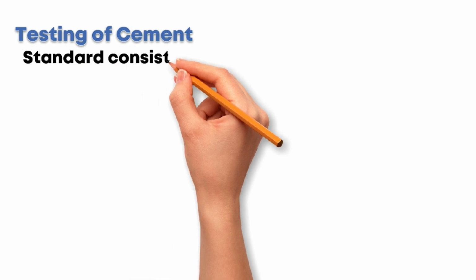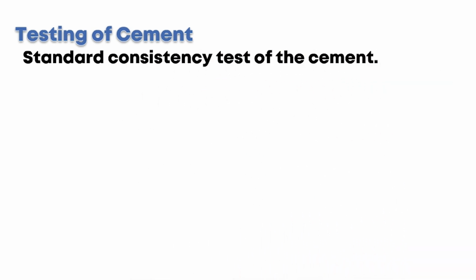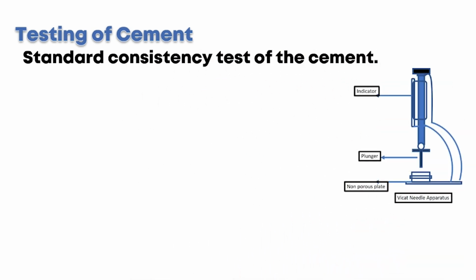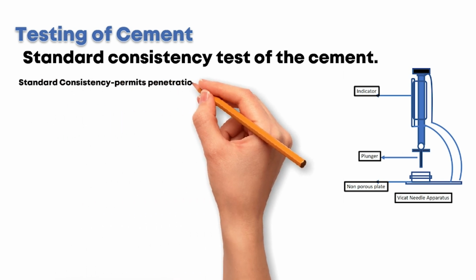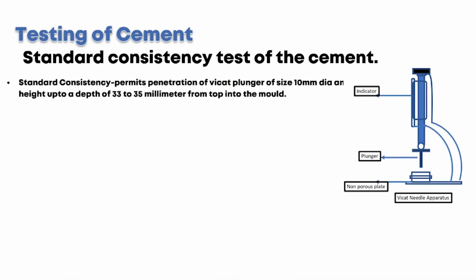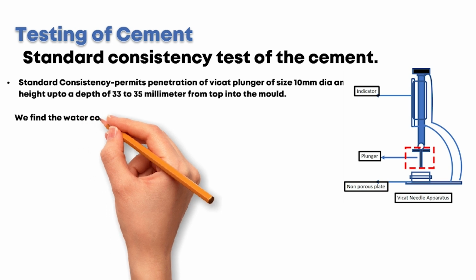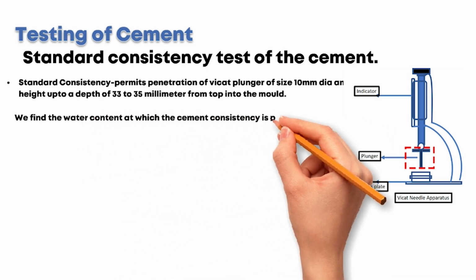Let's discuss the standard consistency test of the cement. Standard consistency should be known before we know about soundness. Standard consistency permits penetration of the Vicat plunger of size 10 mm diameter and 50 mm height up to a depth of 33 to 35 mm from top into the mold. We find the water content at which the cement consistency is produced.